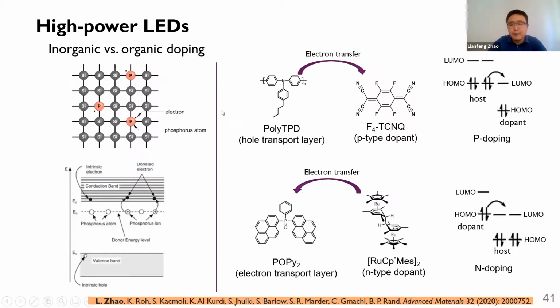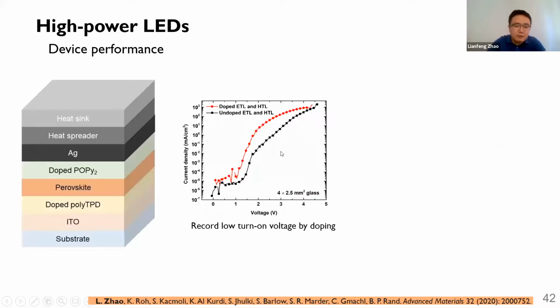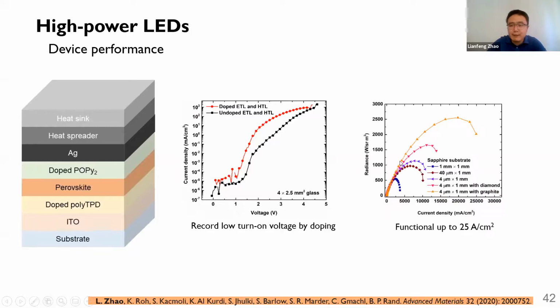Organic doping is different compared to inorganic doping like silicon. It relies on partial charge transfer between different organic molecules. I won't have time to talk in detail, but here we apply both p-type doping and n-type doping to significantly increase the conductivity of these molecular films. In this way, for a given voltage, we significantly increased the current density of the device. And after applying all the thermal management strategies, we were able to operate the device up to 25 ampere per square centimeter. This is actually already similar to power LEDs fabricated based on inorganic semiconductors. And of course, device lifetime is still a bottleneck. In the future, we will further improve the device lifetime for high power application.